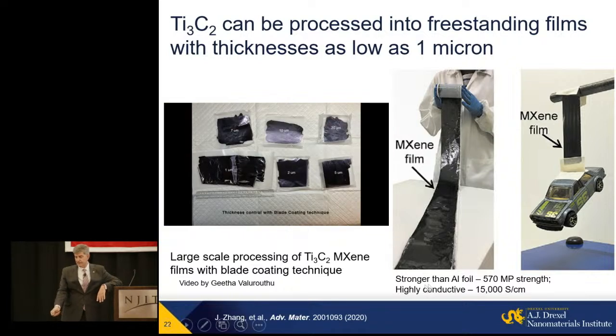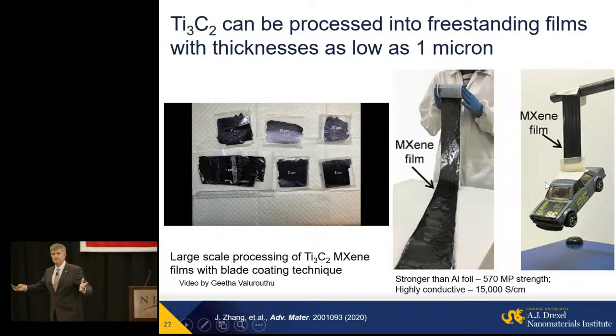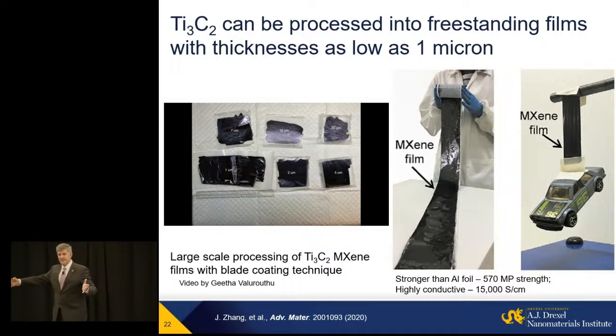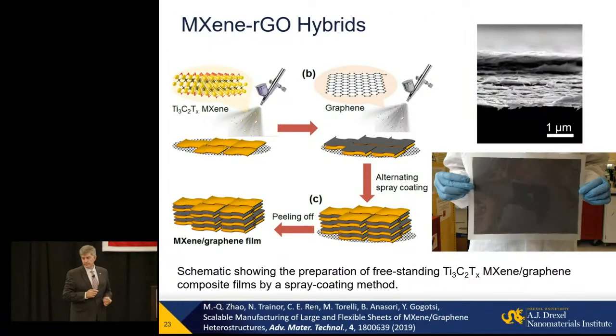What is important? It has the strength of a high quality aluminum, produced at room temperature. Conductivity, at that time in the paper from 2020, was 15,000 Siemens per centimeter. Imagine, for example, batteries. When you replace a 10 to 50 micron metal film with a 1 micrometer film, you cannot easily make a freestanding metal foil at a micron. And you can make it out of MXene at room temperature from solution.